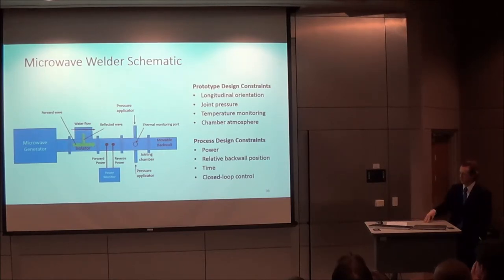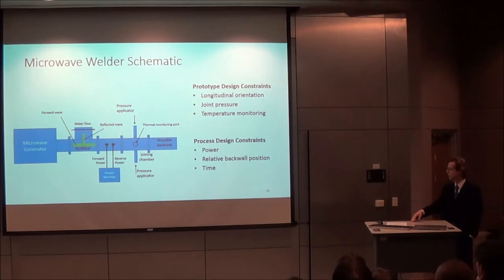In addition, there are several variables we can work with. We can change the microwave power, we can change the relative back wall position, where it's situated with respect to the target, and we can change the overall time of the process. And all of these were incorporated using temperature feedback in a closed loop control system that was developed in a previous work. However, for the scope of this work, chamber atmosphere control was removed, and the closed loop control system was put to the side, discarded, so to speak. It's valuable, but for this work, it was necessary to have a wider operating range in terms of the variables that we can work with, and that control system didn't provide that.